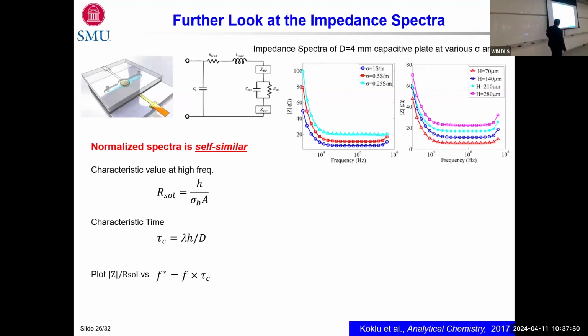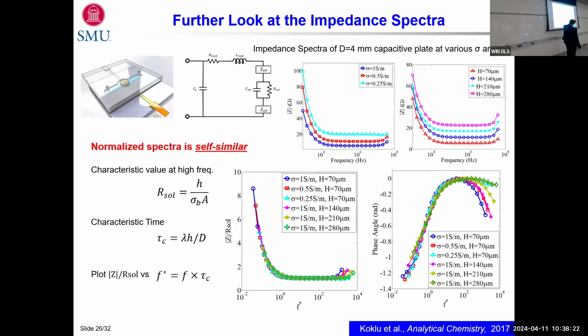Characteristic time scale is a function of the electrode size. The height is basically in between the electrodes, as well as the Debye length, because these are ionized fluids, and it's going to create Debye lengths. High conductivities will be maybe down to a nanometer or so. DI water is about 150 micron or so, I'm sorry, nanometer. So it's very much changing, and it will change the characteristic time. So when you do that, all those things sit on top of each other. Here's the phase angle, starts from negative pi over 2, which shows the capacitive behavior and reaches resistive. And because we don't have inductance in our model, we see these kinds of changes, but we are not as interested in such high frequencies. So all of them can actually be on top of each other.